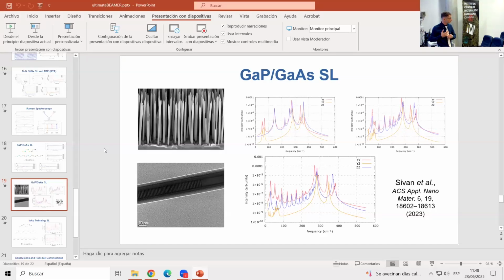So basically you're mapping the Raman tensors with those, right? Can you say that? Not exactly the full Raman tensor, because you're mapping some parts of it for sure. And then in order to map the other parts of the Raman tensors, you would need some sort of rearrangement of the superlattice, right? I would need to show you the precise way in which, like, the transverse optical mode or longitudinal optic mode, the actual way the atoms get displaced and react to the incident light when you shine some laser on them. I would do something like that because it's a third order tensor, if I'm not wrong.